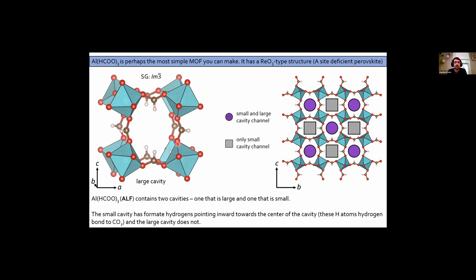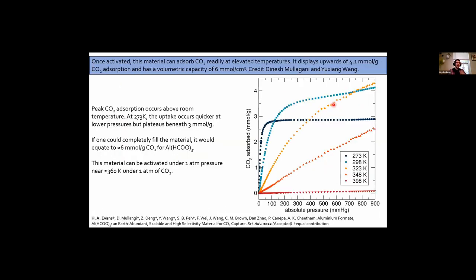The thing that I'd say appreciate for this little short description I have here is that it has two cavities. It has a small cavity and a large cavity. The small cavity is defined by how these formate hydrogens point inwards, and in the large cavities, everything points away, so it's just an empty space. And so if you look down different directions of the crystal structure, you see that it has channels, small and large channels as they alternate going back along the A lattice parameter here, and then those that have only small cavities. And so we activated the material, we've emptied it completely, and we want to put something back in.